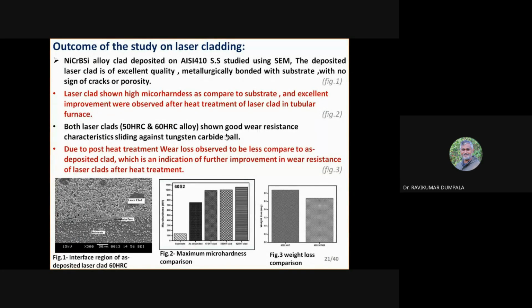which unless it increases the product cost, and it causes other variations. Industry approached us to understand the effect of the heat treatment, so we carried out the study for them, but later they understood that heat treatment doesn't add so much value to the part. It's the cost of an additional process, and heat treatment increases the cost. At the same time, heat treatment also causes distortion in the parts, and the wear resistance is not significantly improving. If you see the next figure, the wear resistance is the weight loss, and the weight loss difference is not so high. For publication purposes it is okay, but to adopt it in industry, doing heat treatment and applying it on the parts is not justifiable.